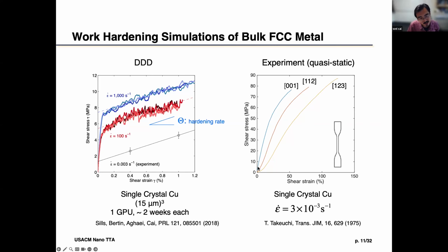I literally tried to extract some data from this curve, okay, by just really getting it from the publication. And what happens, I can only get 2 dots from this curve at this small scale, okay? But the good thing though is that at least if you look at this curve, it is pretty straight down here. So you can also just fit a straight line from there, and that is this straight line. So you can see that actually the slope agrees quite well.